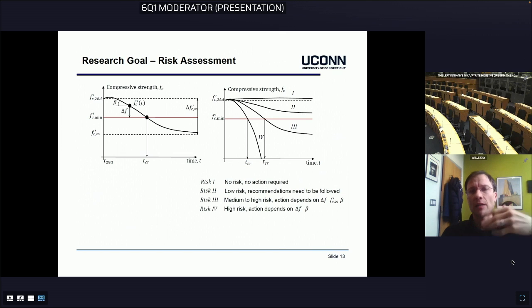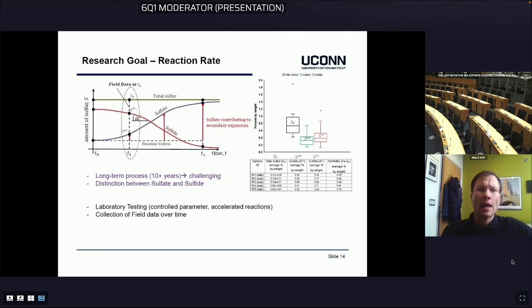And you see on the right side different scenarios. This could be that the strength is not being compromised at all, type 1, or that the strength is somehow compromised over time, but it levels out and never reaches the minimum strength requirement, so it always stays above this. Or scenario 3, that over time it degrades and then goes under, but it will take a certain amount of time. Or scenario 4, where it deteriorates rapidly and there's no real hope to stop it or to remediate it. Next slide.